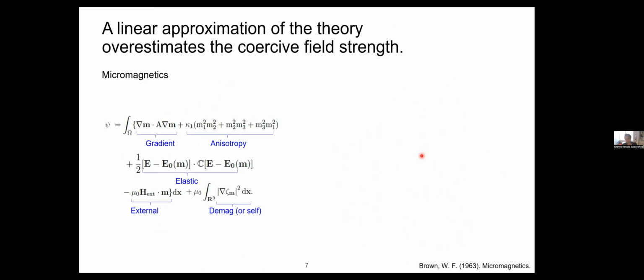And so what we do in this kind of project is to start from a well-established theory called micromagnetics theory, which started with William Fuller Brown quite some time ago. It's a very rigorously developed theory. I say rigorous because it's one of the theories wherein you have very well-defined energy terms, where each of these coefficients directly corresponds to a measured material property, rather than us fitting a curve to any specific parameters. And this theory has been quite well applied and shown to work very well for other magnetic properties, whether in terms of actuation or in terms of microstructure prediction. So this theory is very well tested and validated.